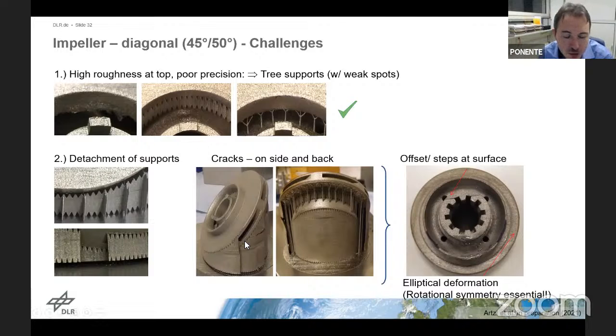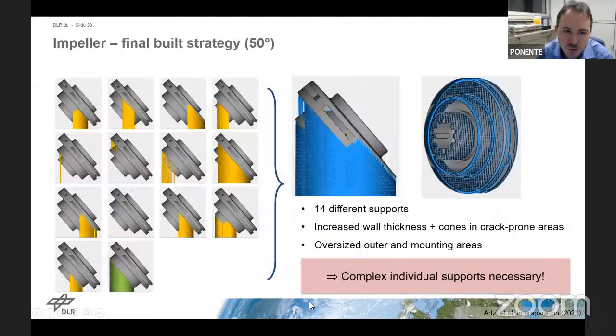And for the other detachment issues due to the high thermal residual stresses, we developed custom support strategies. Here you see some images that show how drastic these thermal stresses can be. Very high stresses, millimeter deformation of the parts, cracking in the supports and things like that occur here. You see some deformation here on the right-hand side. This part is all but round. So we had to work on the supports here.